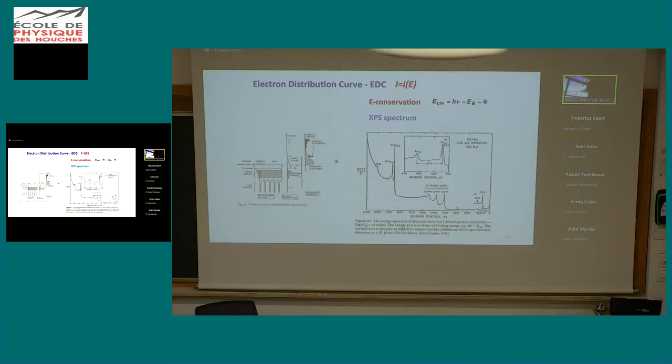This is an X-ray photon going in onto the matter of interest and electrons coming out. So here you have the sketch of the energy levels in the matter: core electrons, then the valence electrons, Fermi level, vacuum level, the work function between the two. The X-ray photon will then carry electrons out into the vacuum, and the electrons will be detected as a function of their kinetic energy, and you will get an intensity structure which is a replica of the density of states inside the matter. You will not only get those, you will get a sort of background which you see here of secondary electrons,